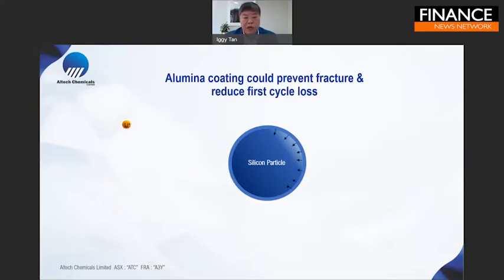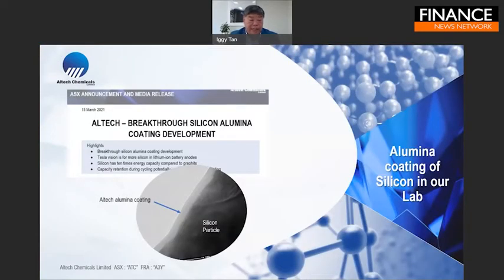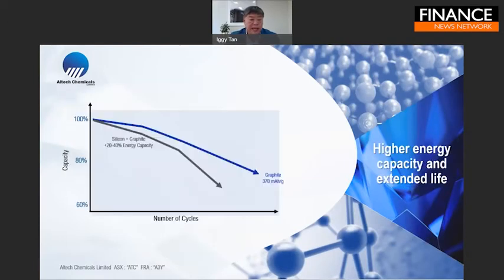We're using our alumina coating on silicon particles, and we hope that it'll contain the silicon particles and prevent them from fracturing. We have now done the test work in our laboratory. We've successfully coated silicon particles with alumina, and you can see the picture there of how continuous that material is. And our hope is that this is what the end result will be. The blue line shows a coated silicon graphite composite with extra energy from the silicon particle and increased battery life.